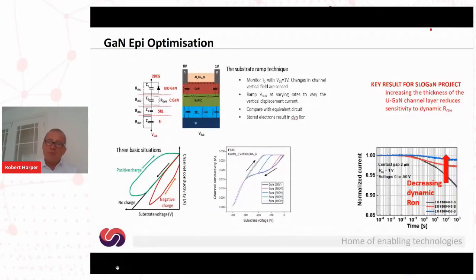And importantly, by making some changes iteratively through this project, we've been able to greatly improve the dynamic RON performance. So you see on the image on the bottom right there that we've been able to modify the epi structure significantly through the length of this project, and we have greatly improved the reliability and the dynamic RON performance. So that's been a really successful outcome, and we're basically finishing this project at the end of June. So it's been challenging. We've been working through COVID restrictions, obviously, but Bristol University and Newport Wafer Fab themselves have managed to stay open and operational through most of that time. So that's been good.